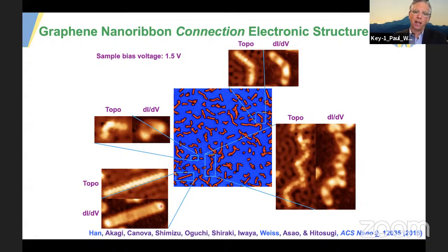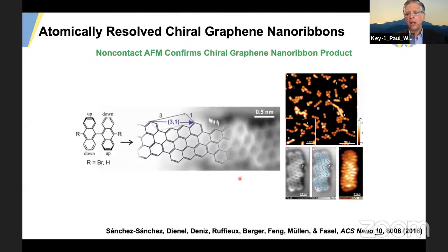So it's hard to imagine making devices that are just straight, although I will say the Berkeley group has come up with a very clever way that one might do that. But what we then want to do is make a combinatorial set of precursors that then form structures on the surface, measure all the different contacts that we get, develop a predictive theory to say, okay, here's how you get the best contacts, and then we can design the precursors that'll snap those together. And we've done some work along those lines already. I'll point out that Klaus Mullen and Roman Fasel jumped into that controversy with a non-contact AFM, measured the structures, and showed that indeed, our mechanism had been correct.